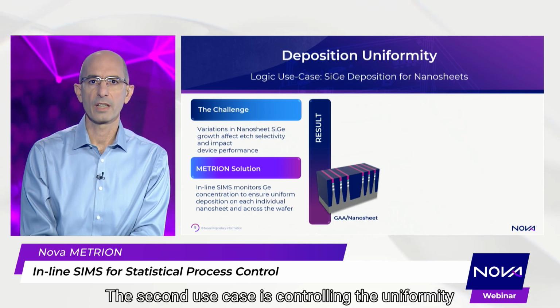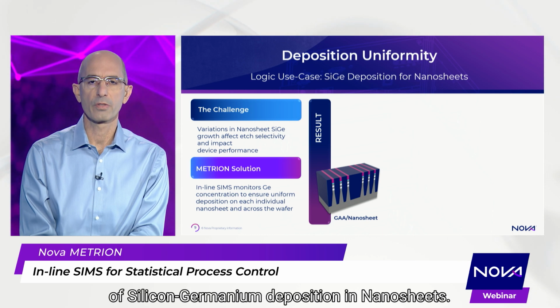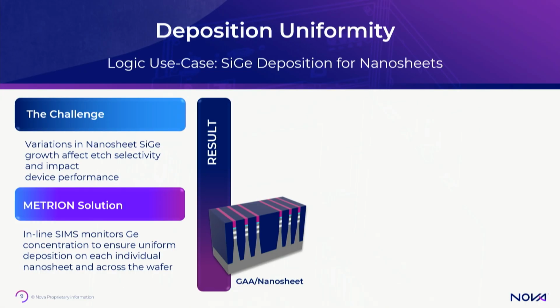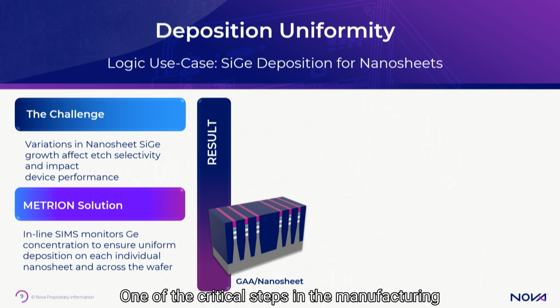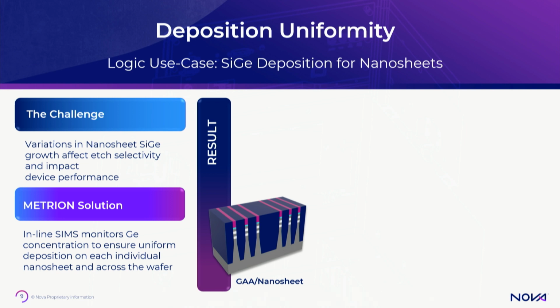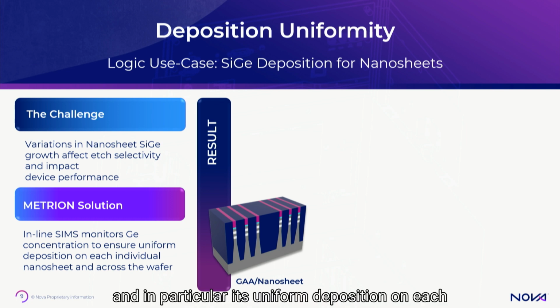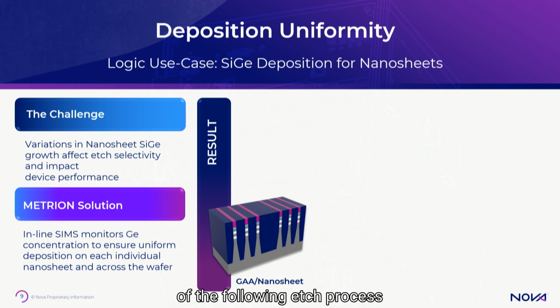The second use case is controlling the uniformity of silicon germanium deposition in nanosheet. One of the critical steps in the manufacturing of nanosheet or gate-all-around is the deposition of silicon germanium. The concentration of the germanium, and in particular its uniform deposition on each nanosheet, dramatically affects the selectivity of the following etch process and has a direct impact on the critical electrical performance of the transistor.